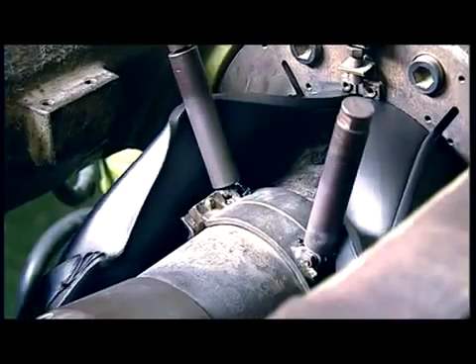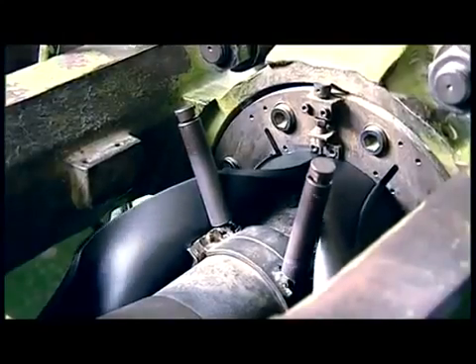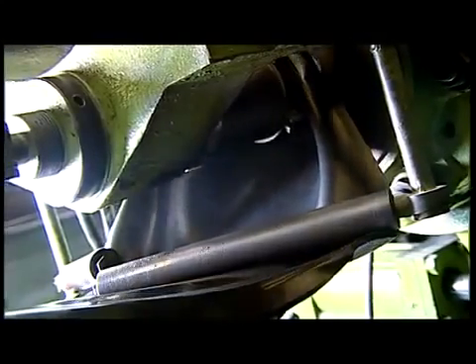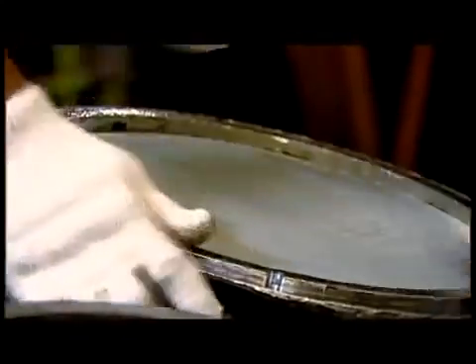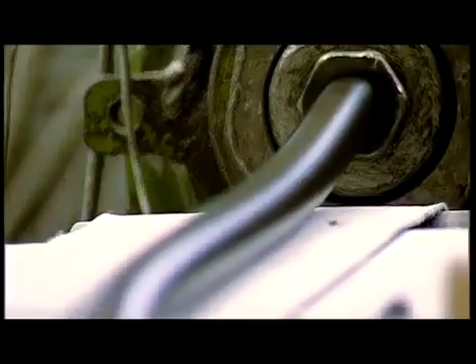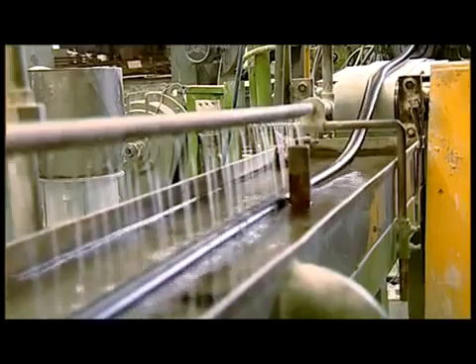The inner tube is made in a similar way to the tire. The base material is mixed, kneaded, and stored temporarily as skins. Besides the high butyl content, and at only 1 millimeter thick, crucial to the airtightness of the strong Schwalbe tubes is the purity of the material. The base material, therefore, has to be pushed at enormous pressure through 7 filters, and thereafter it is extruded as a continuous tube.